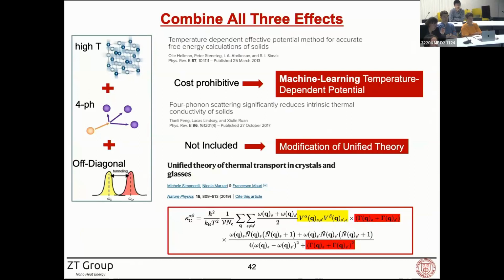Yeah, so the way we look at the temperature is we are doing this self-consistent phonon approach. We first get some normal modes, and then we populate those phonon modes to satisfy the temperature we want. Yeah, but in some ways that takes into account anharmonicity and three phonons and four phonons, renormalizing, say, second derivatives of the free energy rather than second derivatives of the energy.